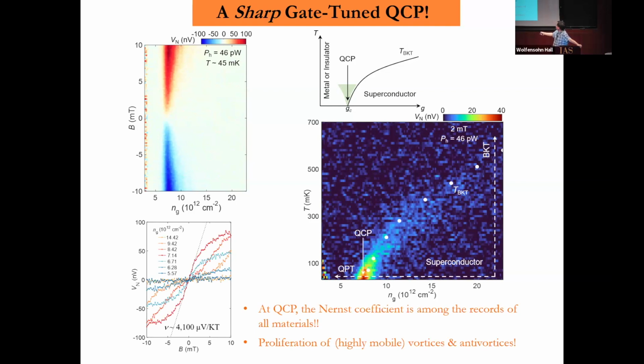How large? This Nernst coefficient, due to the vortex Nernst effect we measured, is one of the largest values among the records of all materials. In other materials, semi-metals with electrons and holes need very high mobility to see a large Nernst coefficient. More importantly, those large values cannot happen from the conventional quasi-particle picture. They do not happen at zero temperature because at zero temperature everything freezes.